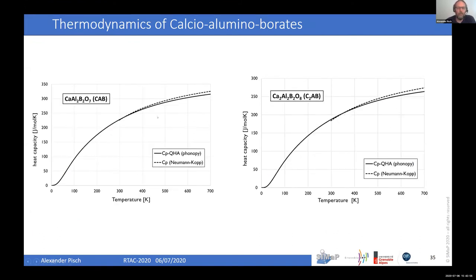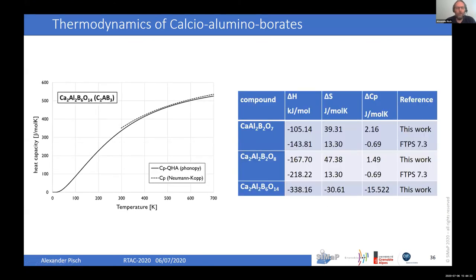And from the heat capacity, not much of a surprise. The dotted line is the Neumann-Kopp rule, so the sum of lime, alumina, and boron oxide. And you see that basically for these two compounds, we get a Neumann-Kopp behavior. So no surprise on that. But then if we go to the natural occurring compound, it's a little bit below. Not much, but a little bit below.